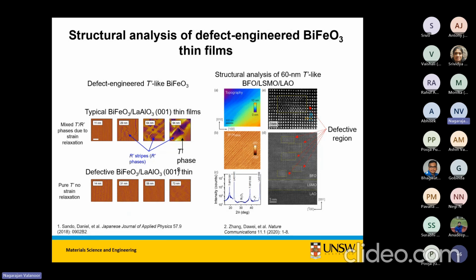When you grow this bismuth ferrite on lanthanum aluminate, now why lanthanum aluminate, etc., please bear with me, I have slides for that later on. When you grow bismuth ferrite on lanthanum aluminate, it puts this compressive stress, and that extends the bismuth ferrite out of plane. It completely changes the crystallography of bismuth ferrite. In the breakthrough paper from Ramesh's group, that strain is only sustained for 10 nanometers.